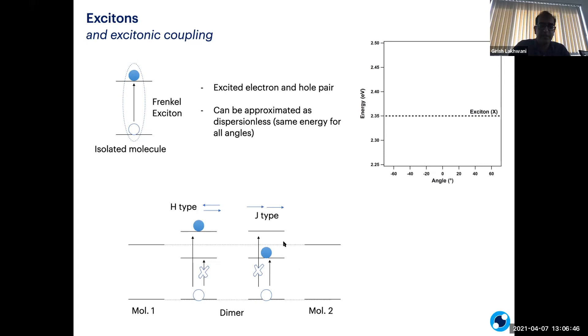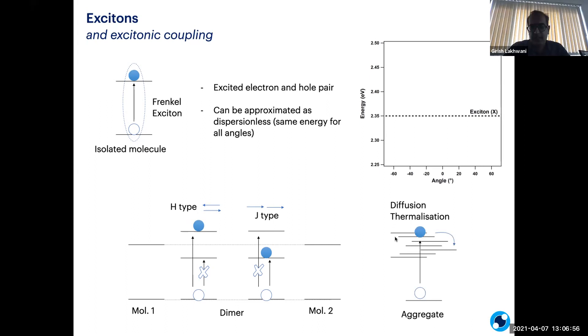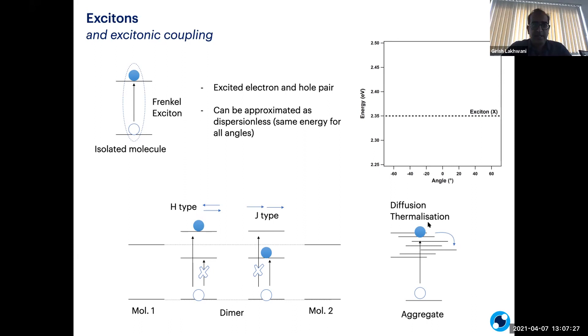When two molecules are brought together, there is an energy splitting often known as exciton coupling, and the energy difference is a marker of any coupled molecular system. When you bring a lot more molecules together, you can see many energy states, different processes — diffusion, which is energy going across different density of states, often also referred to as energy transfer, and also non-radiative thermalization where energy trickles down to the lower vibrational state. In all these scenarios we are dealing with coupling between two molecular excitons.